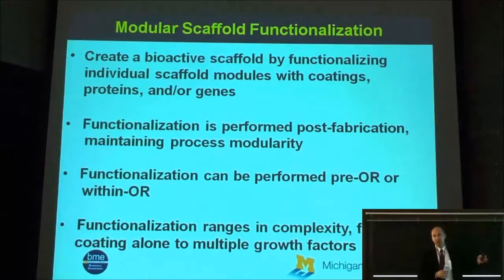So once you've built these scaffolds, you can then do other processes, maybe fluid-based processes or plasma gas-based processes to coat the holes within these scaffolds. So we do this functionalization post-fabrication. Typically, you do it pre-operating room. But if you're applying cells, because of regulatory issues, you may want to do that within the operating room because of less regulatory difficulties. Because you can build these things in physical modules, you can apply different growth factors to different modules and then put them together.